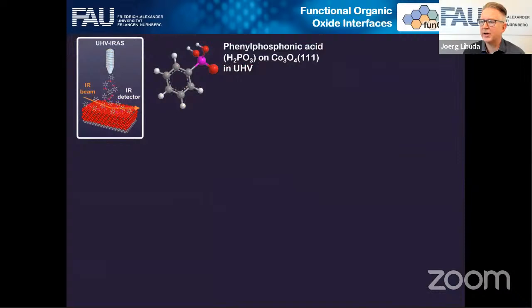So can we use this model approach to understand these interfaces? Yeah, what we can do is we can make these interfaces in ultra high vacuum and understand how these molecules bind to the surface. And this is a first step here in this direction. We take a test molecule, the phenyl phosphonic acid, and this molecule carries these phosphonic acid groups. And that's a very strong anchor unit that allows you to attach a molecule to an oxide surface.